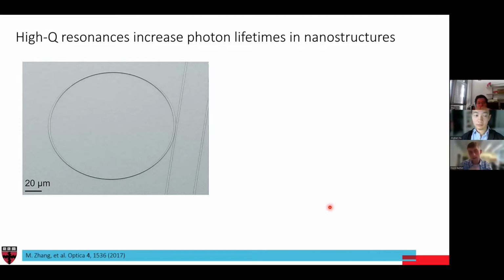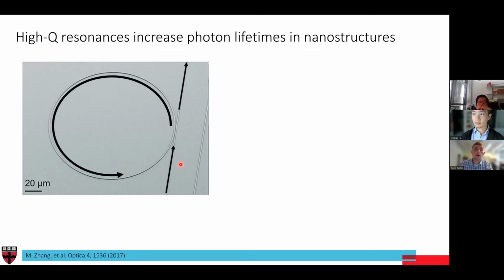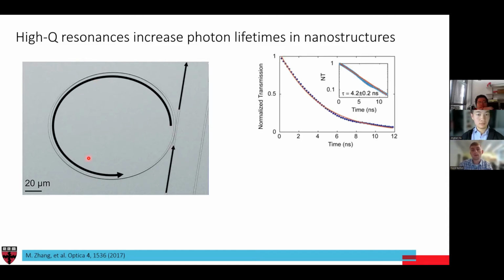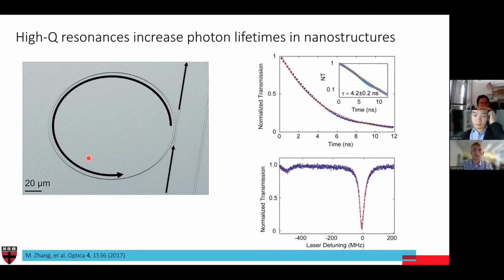This is actually a structure of an optical waveguide on a chip connected to this large ring. This ring is a cavity that will trap the light inside it for a long period of time. And so light will propagate along this direction in the chip, and then it will end up coupling into this ring and circulating for a long period of time. And you can compute or measure the lifetime within the structure, and researchers can find in this case that the light is actually trapped in this 100 micron structure for several nanoseconds, which is extremely, extremely high.